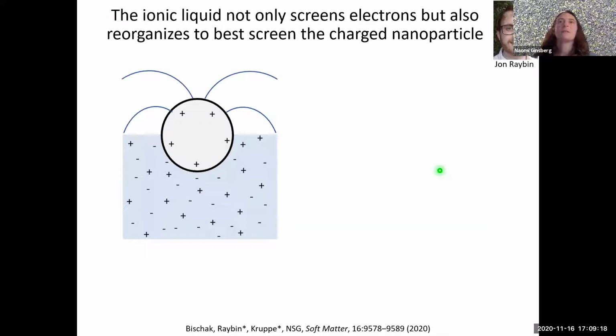Okay, so this is going to become more complete once I talk about interfacial interactions as well. But for now, just focusing on the charging alone, I'm sure you'll appreciate that if you have a charged particle and it's partly exposed to vacuum, its field lines that go through the vacuum can't be shielded. And this scenario is likely not the equilibrium state of the system if there's substantial charge on the particle. So given we already saw that the interparticle interactions don't change as charge accumulates on the particles as time evolves, the ionic liquid must be doing a really good job at being an ion conductor, which it is.